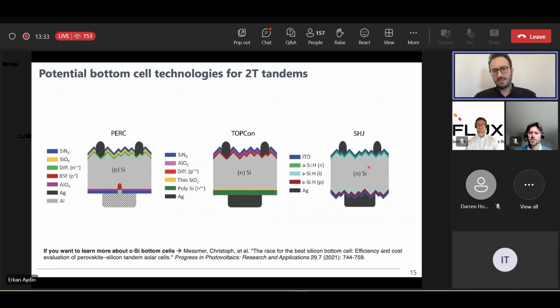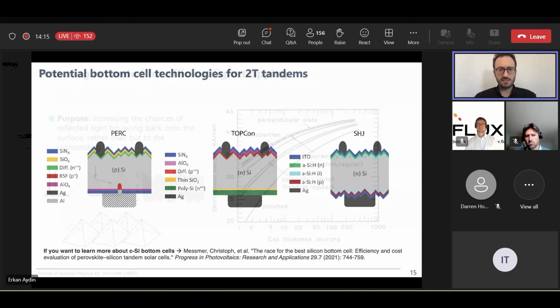But on the other hand, if you look at the right-hand side, silicon heterojunction is also quite promising, and we can do double-side texturing with this configuration. Basically, we have symmetrical passivating contacts on the front side. We have directly transparent conductive oxide. We don't need to fire through these front electrodes, so we can use the front TCO directly as a recombination layer. That's why recently the majority of the works in the perovskite-silicon tandem field are coming from silicon heterojunction, so basically we are getting a better spectral response, minimized reflections, and it is also easy to fabricate.